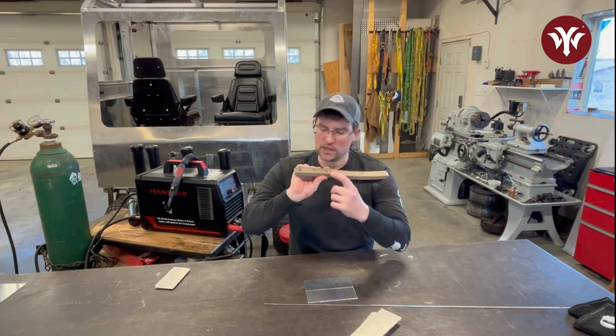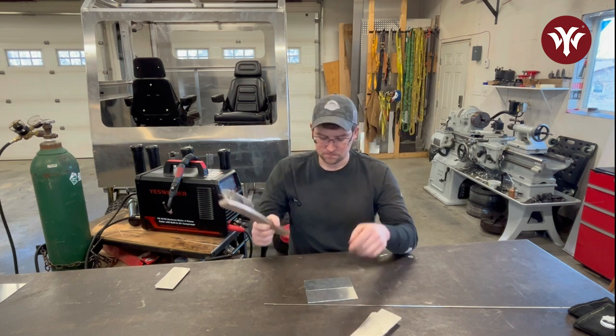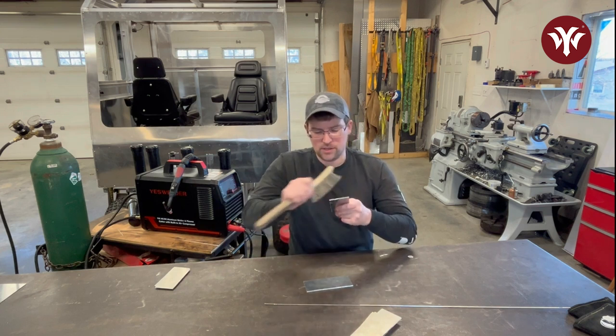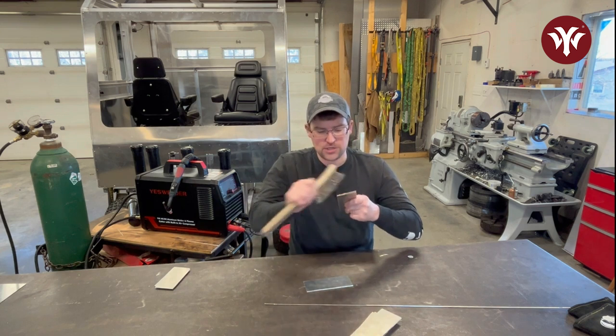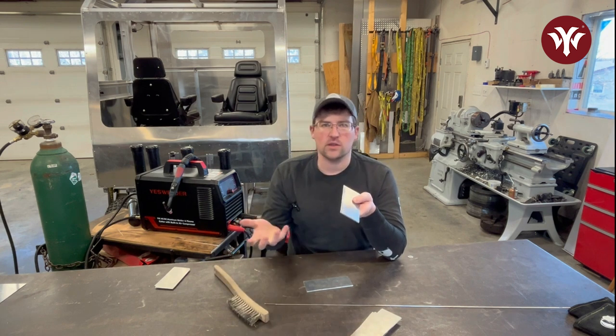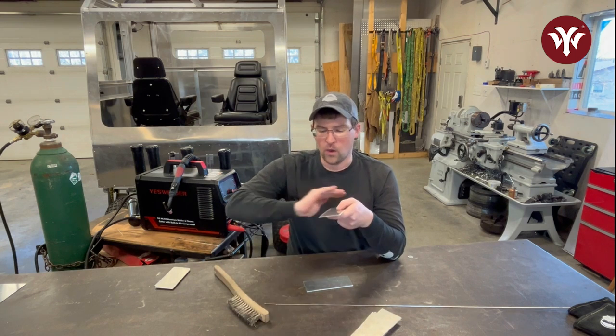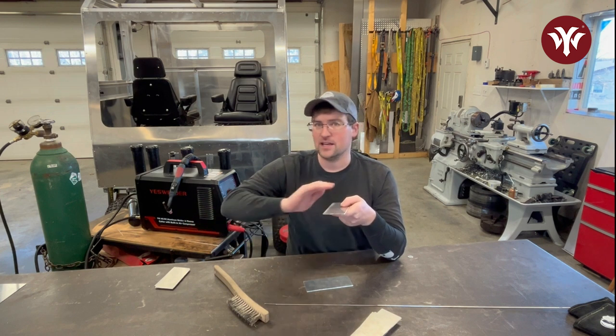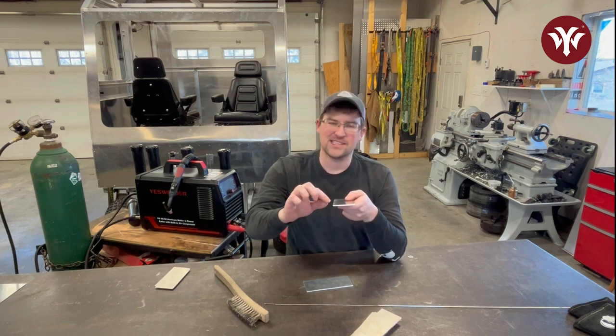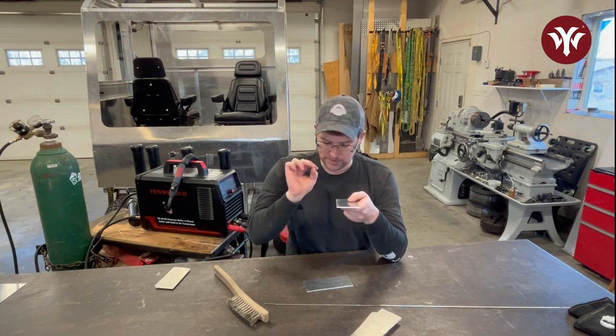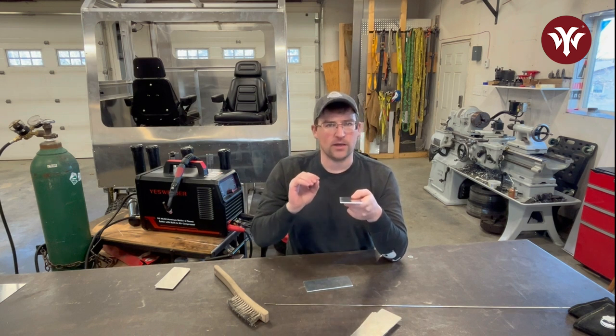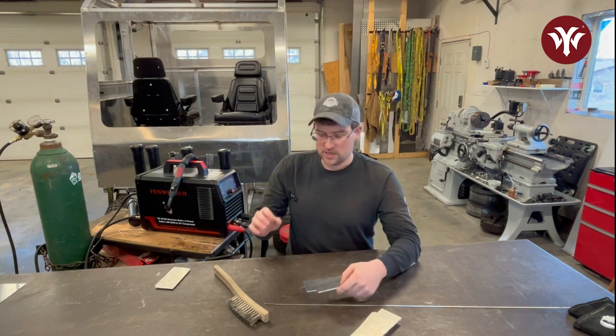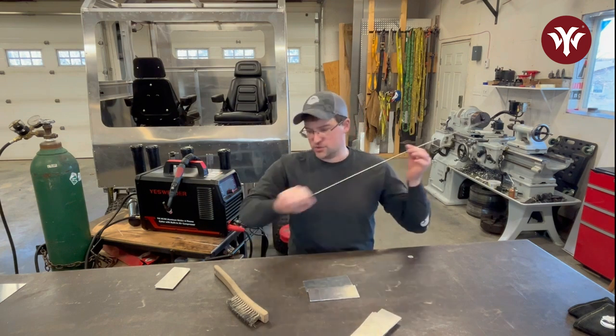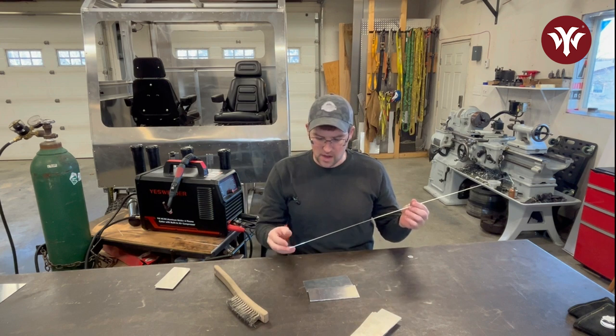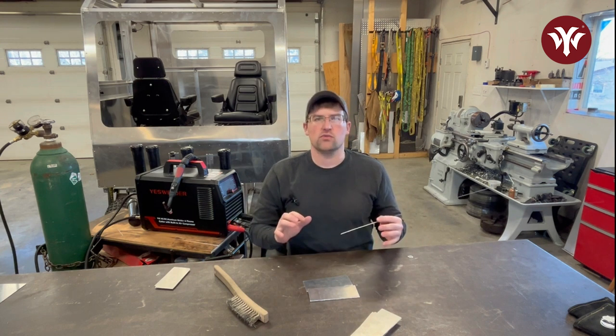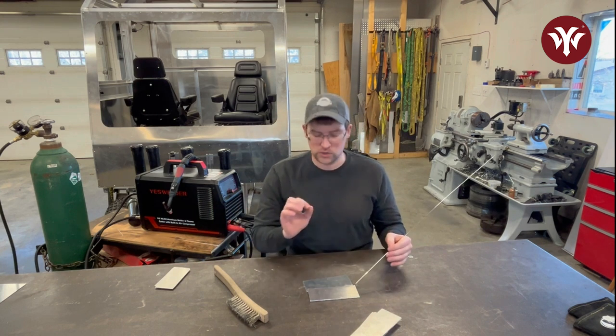Get yourself a dedicated wire brush, right on it, aluminum, and wire brush that oxide layer off. Just scratch it up, and then when you've done that, go ahead with a nice clean rag and some acetone, wipe off all of that oxide dust and any oils that would be on there, and then you have nice, clean, exposed, bare aluminum. And when you strike that arc, it's going to puddle up really quickly and fuse to the other part. And when you add filler, which I also suggest wiping down with acetone, you'll see why, it will just blend in really easily and your puddle's going to flow really good.